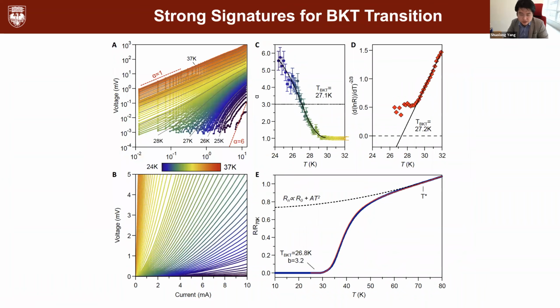On the other hand, let's also consider a different effect. Monolayer iron selenide is a 2D superconductor, so it's subject to something called the BKT transition in the 2D limit. For those of you who know about this, it means that you can never get the true coherent macroscopic superconducting state in the 2D limit, but instead you get vortices. At sufficiently low temperature, these vortices form vortex-antivortex pairs. Even though that's not a totally homogeneous superconducting state, it has no dissipation, so you can still enter the zero resistance state. This is what we call the BKT transition. It's deeply connected to superconductivity, but not exactly the same.